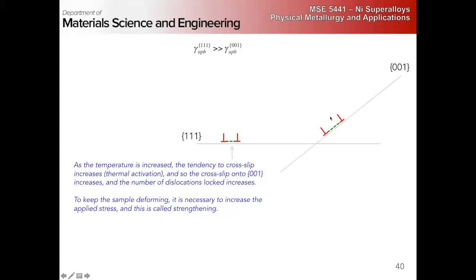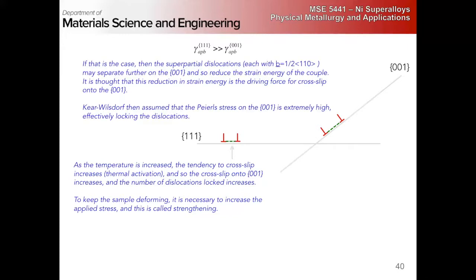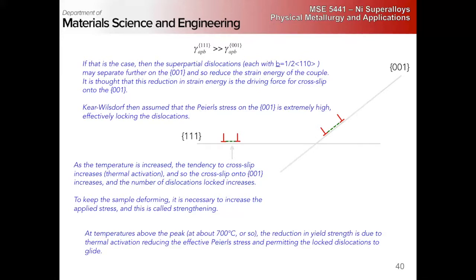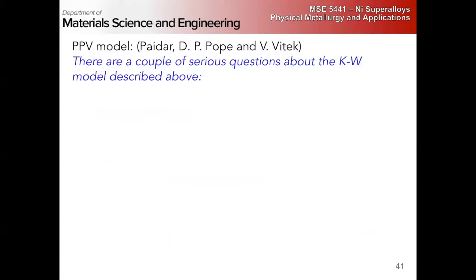And so essentially, they can't glide on the cube plane, right? They're sessile. So these dislocations are now locked, right? The only way we can get them to move is to increase the applied stress, and therefore strengthen it, right? Okay. So now what happens once we get above the peak? We now have enough thermal activation to reduce the critical stress, and are able to move these dislocations, permitting them to glide primarily by cross-slipping back onto the 111 planes, right? So that's the idea.